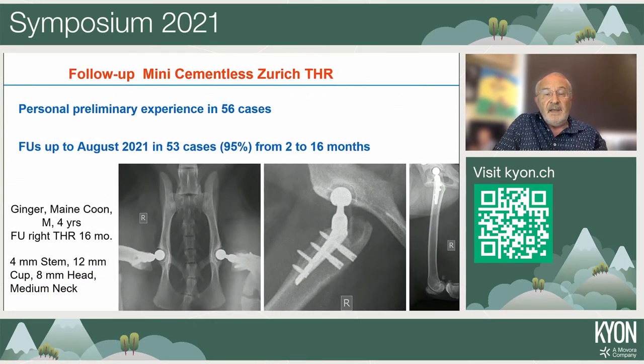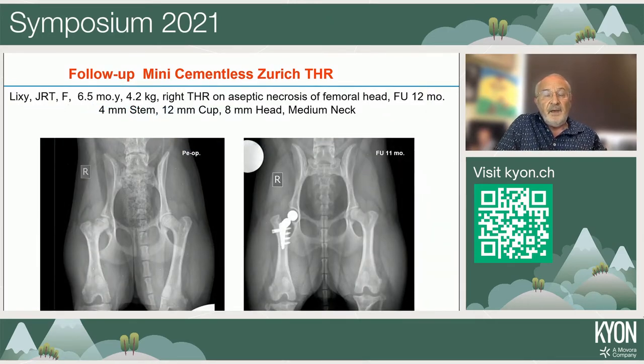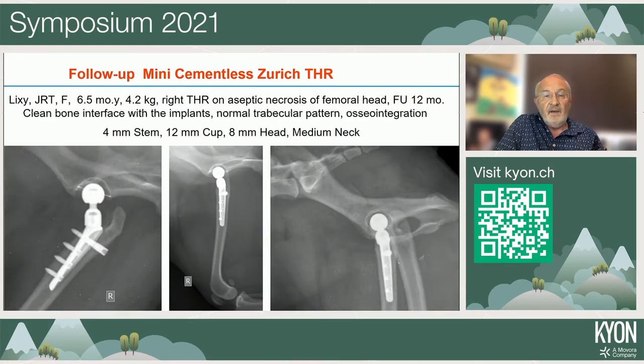My experience accounts for a good follow-up because 95% of my cases got at least one follow-up at 2 months, and several of them a longer-term follow-up, up to 16 months. That was the first cat I did, the right side, as you can see in this case, Ginger, and that is the follow-up at 16 months. And the longest follow-up I have in dogs is 12 months, and it is a Jack Russell Terrier. These are the views, the mediolateral view and the lateral view of the pelvis.